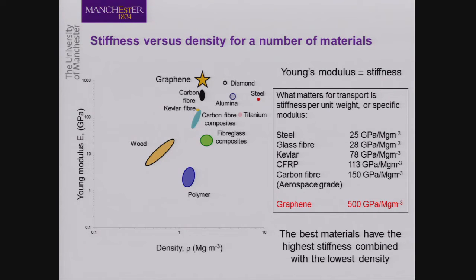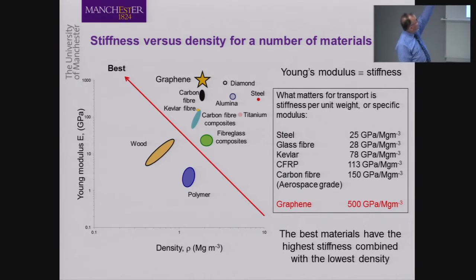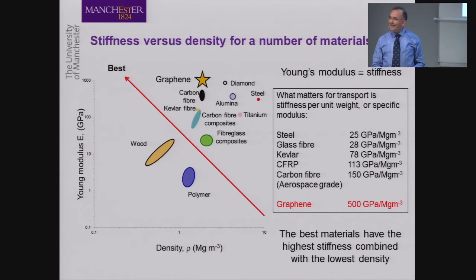And then when we look at the comparison of graphene with other traditional materials, we can see that graphene is at the top left corner with very high stiffness and very low density. So you can see where the traditional carbon fiber is much lower. And of course, if we look at steel, it's got a specific stiffness of 25 units compared to 500 units for the graphene. So it is a super material.